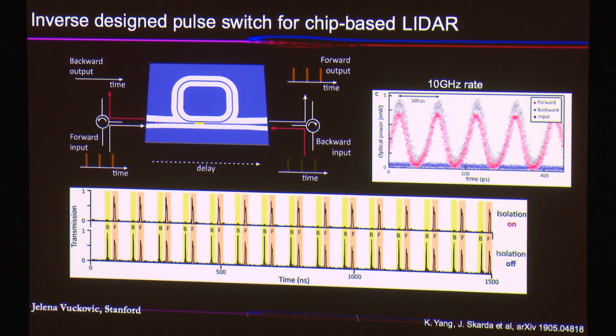So here is the experimental result showing that that is exactly happening. It's the same system, but measured in the pulse regime. If you are in the right range, you see that reflected pulses in the yellow slots are blocked. They're not really coming back to your source, and your forward pulses are going through. And then if you are outside of that dynamic power range where isolation works, then your backward propagating pulses are not blocked, right? So you're not really blocking anything.